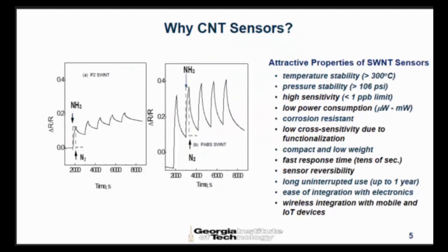So this is an example of sensors that Elena, my collaborator, published. There are two graphs here. These are pure CNTs deposited on an interdigitated capacitor. And this is functionalized CNTs specifically to detect ammonia. You can see that when there is ammonia exposure, the resistance increases, and when the source of ammonia is removed, the resistance decreases. And this can cycle on and off depending on the exposure time.